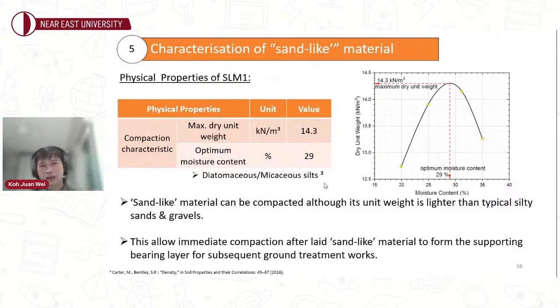Next one, this is the compaction characteristic of the SLM1, where we use a modified Proctor to conduct the test. And this is the graph showing the maximum dry unit weight and the optimum moisture content. This value is comparable to diatomaceous and micaceous silt. Although it is slightly lighter than typical sands and gravel, the graph shows that our SLM1 sand-like material is comparable and can be used to support whatever is loaded on top of this bearing layer.